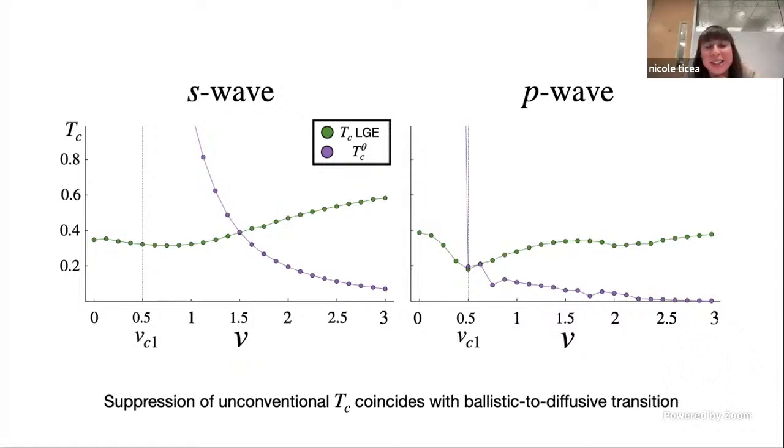So Anderson's theorem, in the original paper that he wrote, was all about S wave. He was just trying to argue why S wave superconductivity can occur despite disorder. Yes, exactly. His original paper was just about S wave, and people since then have talked about the implications for non-S wave superconductors. But my answer is that Anderson's theorem is probably not extraordinarily useful in practice, because it's really only a statement about the weak coupling instability, as T goes to 0. If you have finite temperature and finite strength couplings, then there are other explanations.